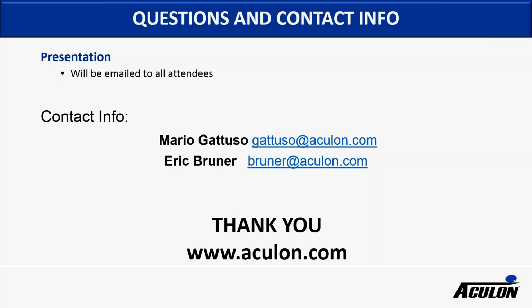Next question is, are these coatings suitable for a fiberglass radome covering antenna to prevent ice buildup? And if they are, how durable are they with exposure to UV? So that's a good question. We've looked at ice prevention several times, and these treatments are going to lower the surface energy of a part to prevent adhesion. But they're not going to prevent condensation or ice from forming on a surface. So ice and condensation are still going to form on a surface, and it's possible that the reduced adhesion could help that ice to fall off, and it just kind of depends on the substrate and the part.